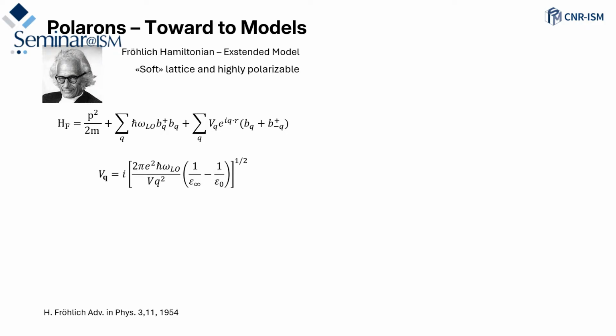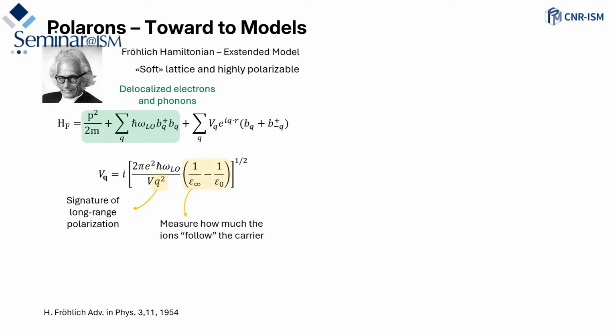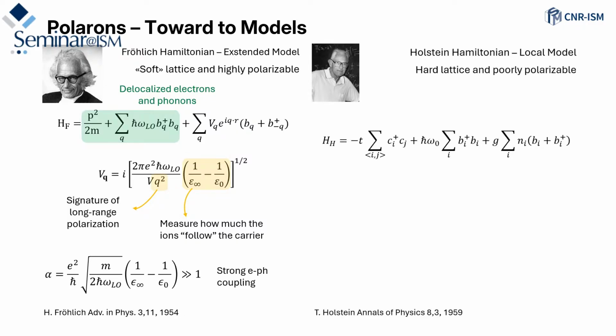The first one who attempted to include this kind of polaron in a theory was Fröhlich, who did it for a soft lattice, so highly polarizable. And what we have in the Hamiltonian is just the delocalized electron and phonons. And the term of interaction between them has this behavior, which is 1 over q, which is a signature of long-range polarization. And this term, which also appears in the alpha constant, tells us how strong the electron-phonon coupling is. And this term measures how much the ions follow the carriers. On the other side, this approach doesn't work well when alpha is much greater than 1.